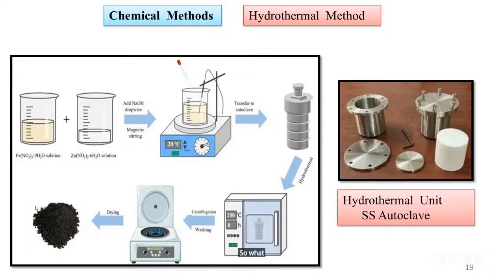So what is the difference between the precipitation method and the hydrothermal method? The hydrothermal method is considered a more advantageous method in contrast to the co-precipitation method because when you keep this material in the furnace, due to the autogenously exerted pressure and temperature, the nanoparticles have good dimensions as compared to the co-precipitation method. I have actually compared the same material from precipitation and hydrothermal. The desired lattice was obtained after the hydrothermal synthesis. So this is a very good method, but it requires apparatus. It is an extension of the co-precipitation method.